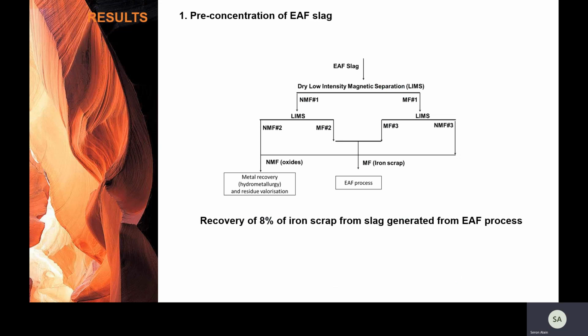Before processing the EAF sample by hydrometallurgical treatment, a preliminary pre-concentration step was performed. It consists of dry, low-intensity magnetic separation in two stages and allows recovering 8% of iron scrap, which can be valorized in the electric furnace.